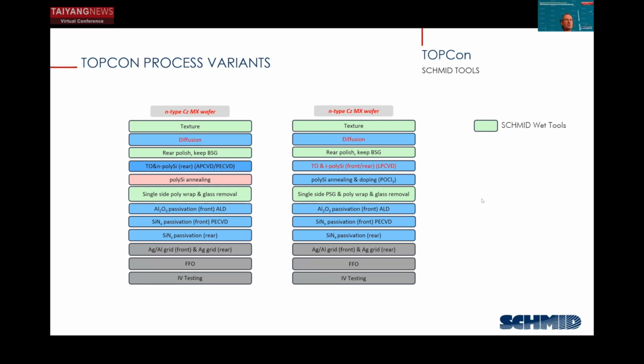Coming to the TOPCon, which is a major topic of this conference, we also see, aligned with the other speakers prior to my presentation, that typically you do see two process routes. One is the LPCVD driven, which historically was the first one that came into mass manufacturing, is still dominating, but slowly replaced by the PECVD process shown on the right side. Main difference here, we do see that the LPCVD is typically done with ex situ doping versus the PECVD that is using the in situ doping process flow. But as you can see with the green boxes here, we do support both processes with our SCHMID wet tools.